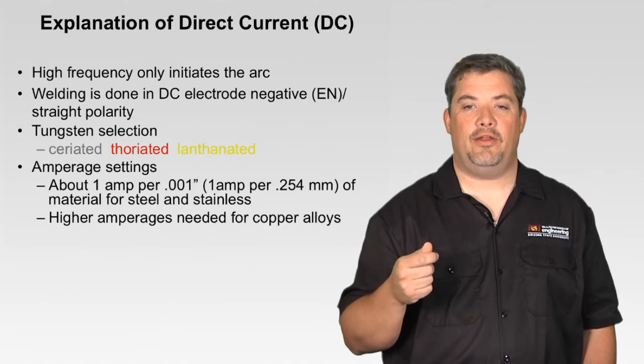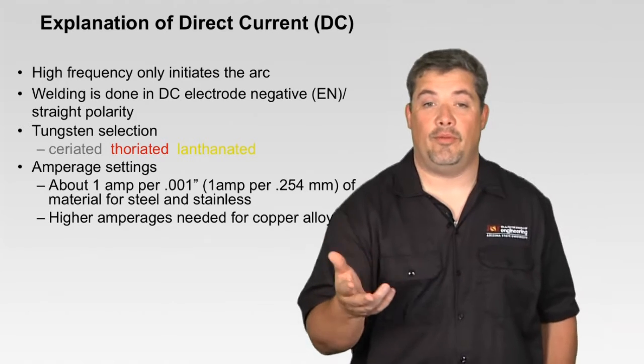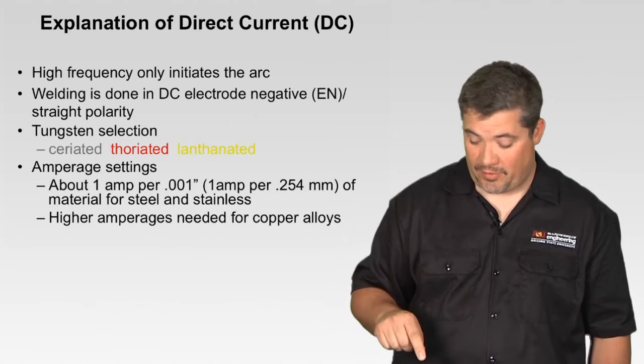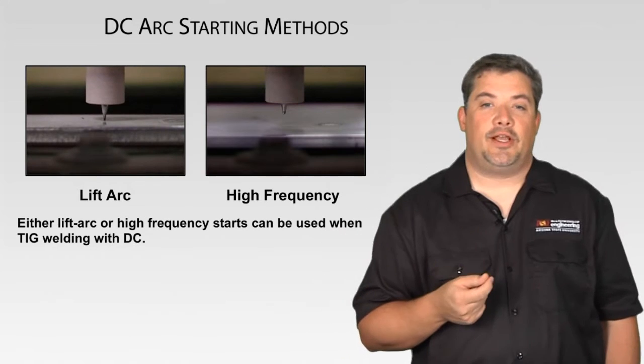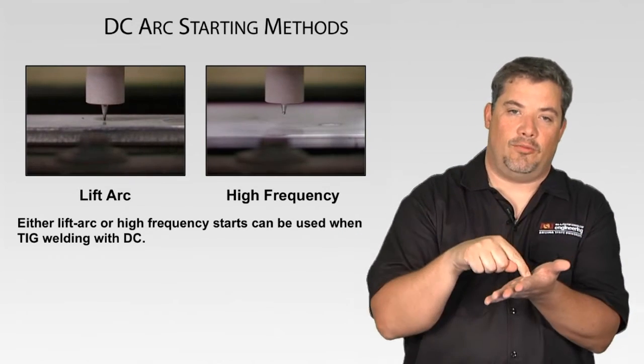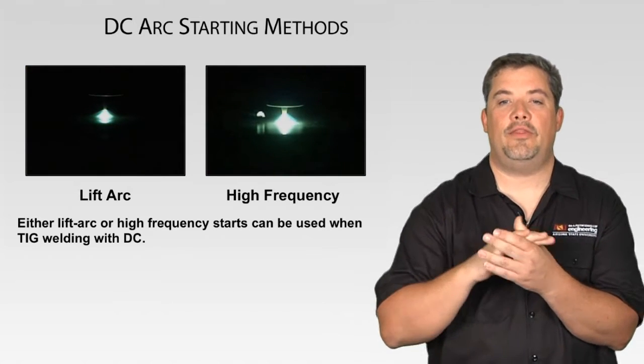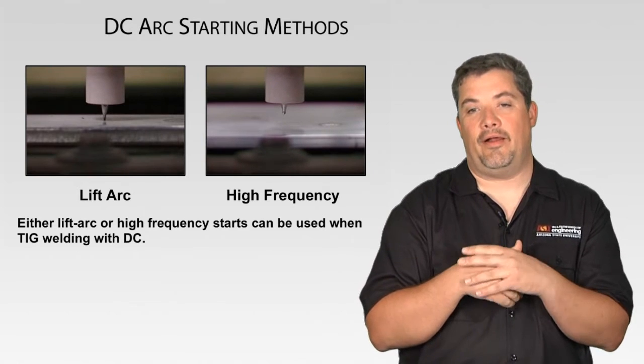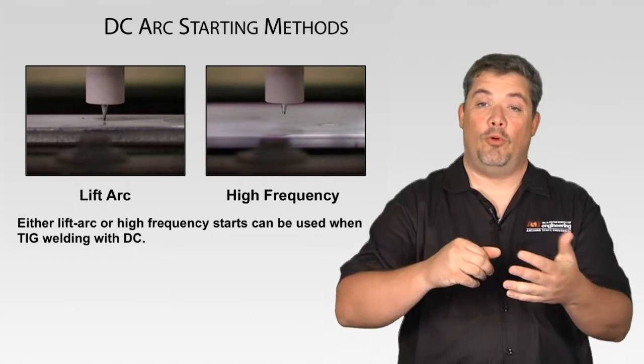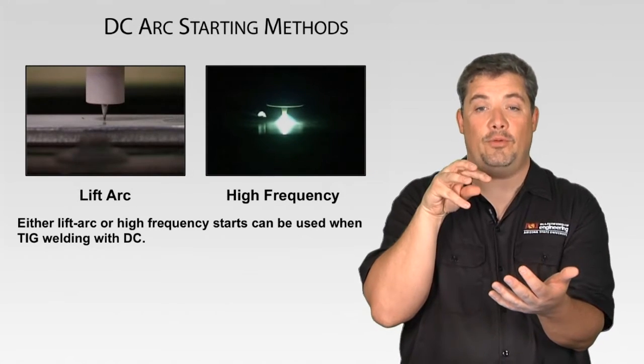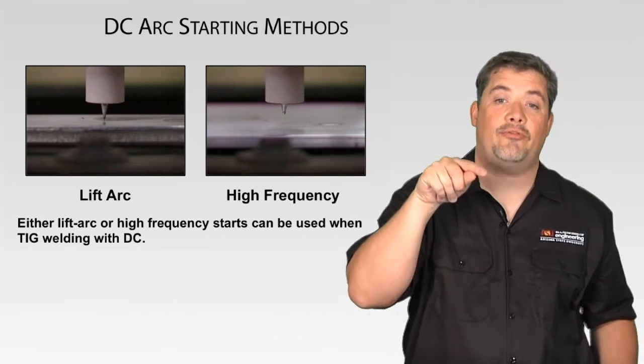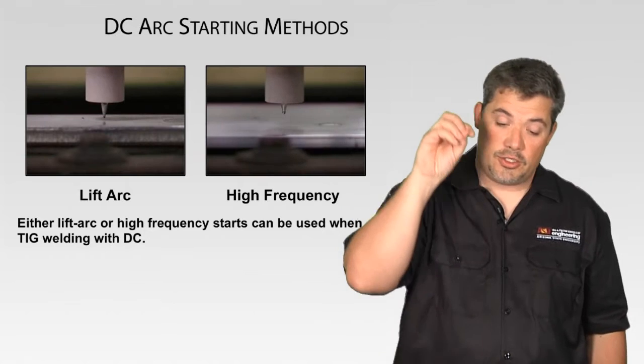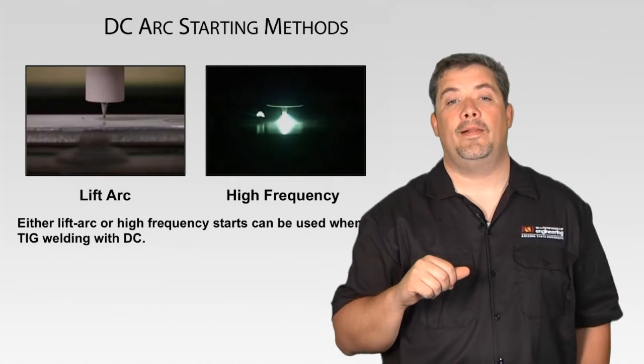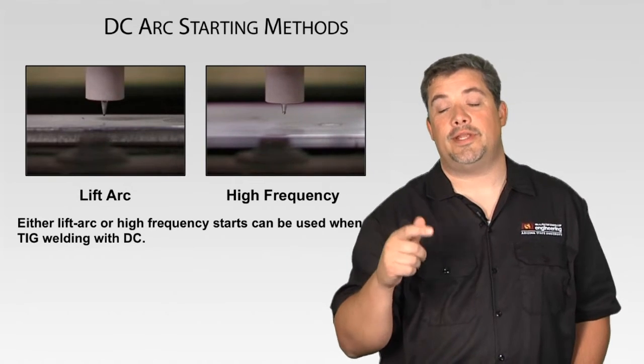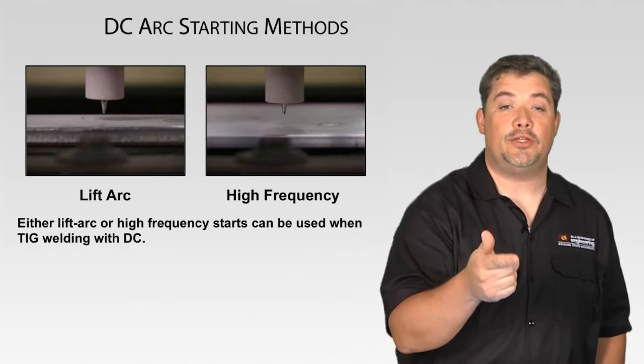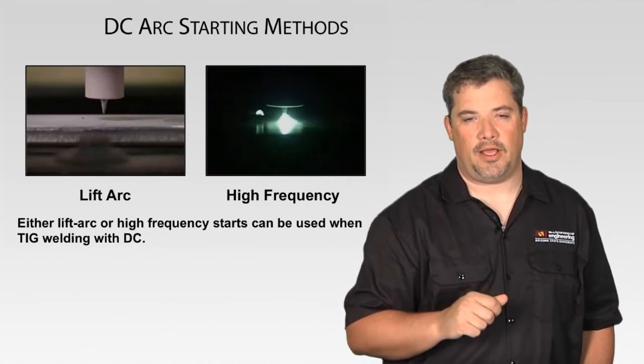Higher amperages are needed for copper alloys than this chart explains, but that 1 amp for every 0.001 inches seems to work for everything except copper. So when we're in DC, there's a couple of arc starting methods. There's lift arc, where you literally touch the tungsten to the work, lift it up, and it strikes the arc. And then there's high frequency. High frequency is a very high voltage, very low amperage, with voltage being the electromotive force that jumps an air gap. That high voltage, high frequency jumps the air gap and then creates a path for the low voltage, high amperage welding arc to jump that gap and strike the arc. So high frequency is a great tool, but it can also take out computers and more sensitive components. So sometimes using tools like lift arc are a great thing in DC to start that arc.